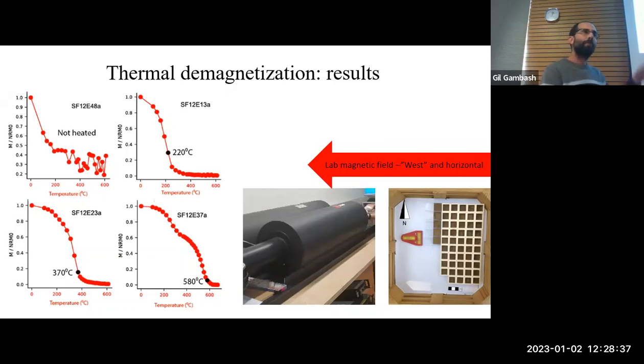And then we gradually erased this magnetic field. How did we do that? We heated them again in the same oven, but this time in a zero field environment, to 100 degrees, and we measured the magnetic signal, then 130 and measured, and again, all the way up to 700 degrees. We did this to all of them, including the control group, which was not fired at all. It didn't record any magnetic signal in the oven.